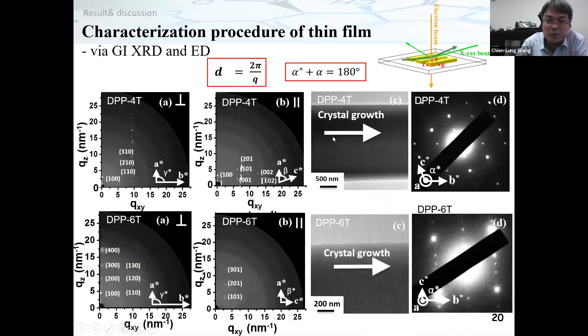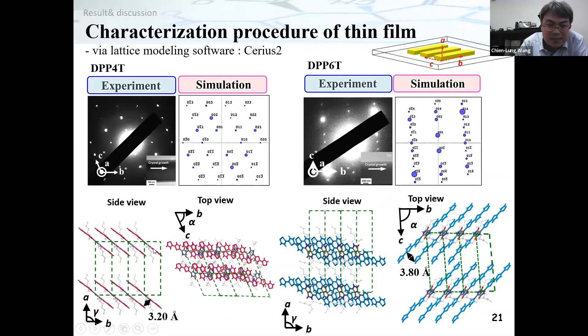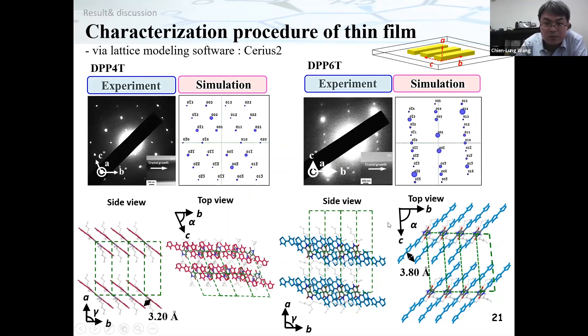After many trials, we generated simulated patterns similar to the experimental ones, allowing us to identify the packing structures of both molecules in the crystal array. We found that both molecules can give mobility because their pi-pi stacking direction is aligned along the charge transport direction. This is a reasonable result. But it also made it difficult to understand why the shorter molecule gives higher mobility, since the longer one actually provides more pi-pi stacking overlap area — which should, in principle, give higher mobility.